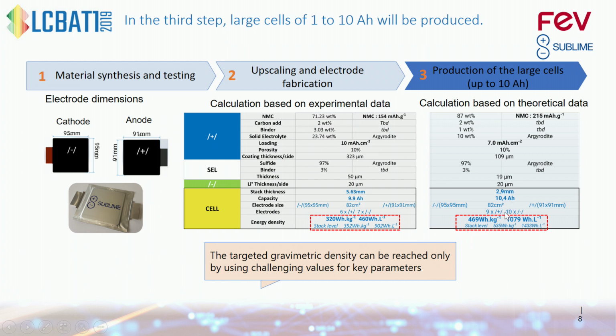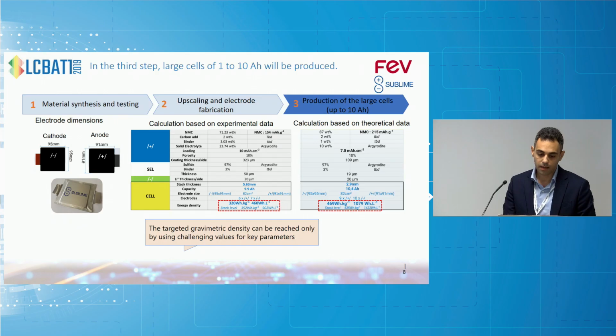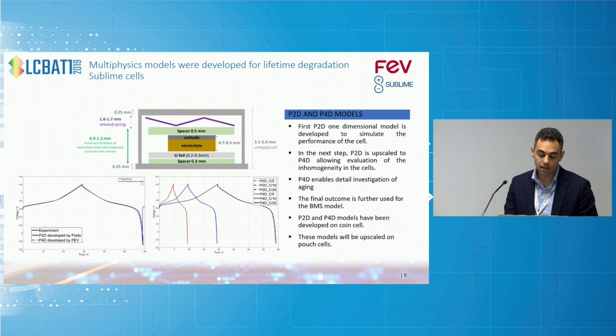If you want to really achieve the end goals, you see we have to reduce the electrolyte content in the cathode to 10%, with a very high NMC content of 87%. Mass loading is a bit more acceptable, 7 milliampere hour per square centimeter, and then we have to really stick to 20 micrometer thickness of the solid electrolyte, and using all of these criteria we can reach the target. So it is very challenging, as you can see here. The next steps will be discussed in the upcoming sessions.